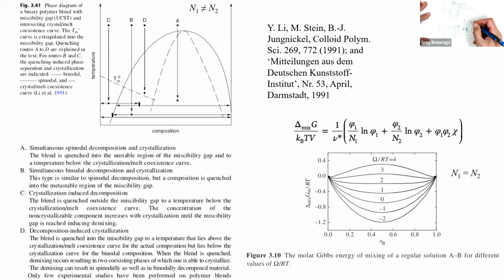So again, it's similar to the eutectic decomposition. In order for this guy to move up there, it has to diffuse. So there's a kinetics issue here, like diffusion, and there's a thermodynamic issue, like either the Hildebrand or the chi parameter. So there's thermodynamics driving it up the hill, and there's a diffusion that's slowing it down. And the concentration gradient is negative, so here the diffusion is opposing the phase separation. Because you have a competition between the thermodynamics and the transport, the spacing of these things becomes a number that you can calculate.